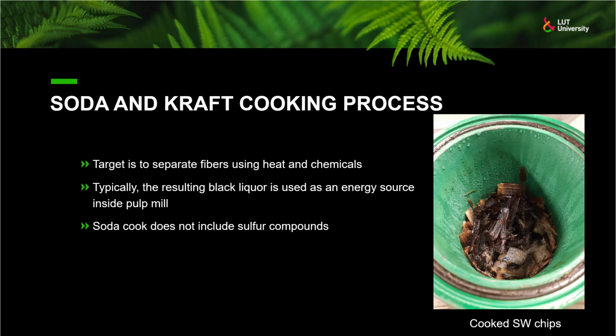Soda and kraft cooking process. Lignin bonds fibers together. It is located both within and between fiber cells. During the cooking process, heat and alkaline chemical solution dissolve lignin. In sulfur-free soda pulping, the cooking chemicals are sodium hydroxide with some sodium carbonate. In kraft pulping, the cooking solution, white liquor, is composed of sodium hydroxide and sodium sulfide. During cooking, lignin dissolves into the formed black liquor. This byproduct is used as an energy source inside pulp mills, burned in a recovery boiler.